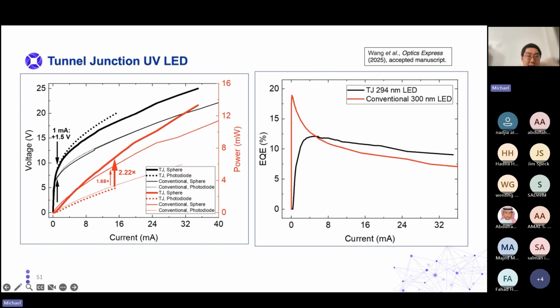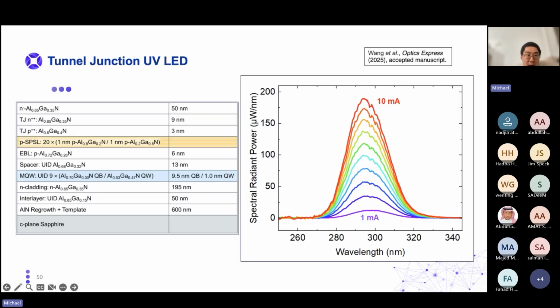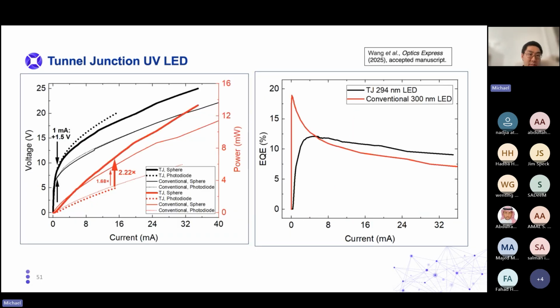It is clear that this contact is fully transparent, as there is no p-type gallium nitride in here, and the only aluminum gallium nitride that is lower composition than the emitting wavelength is this 20%, 1 nanometer layer in the p-type short period superlattice, which doesn't absorb much light at all due to the very thin layers, which due to quantum confinement will push the absorbing edge much higher than what the actual band edge is. So what we found was comparing this tunnel junction